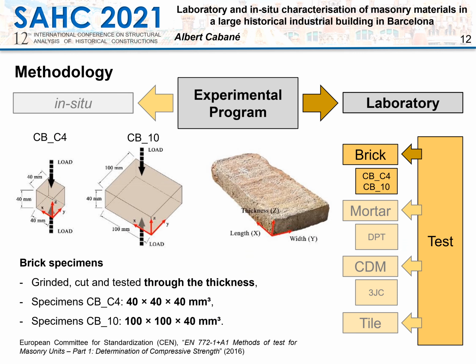The laboratory experimental characterization was carried out on the specimens produced with the extracted masonry components and core-treated masonry samples. The specimens were prepared according to the procedures specified in the European standard. Polishing the load surfaces until a constant thickness of 40 mm was obtained. At least 6 bricks were considered for every extraction zone, and 2 standard specimens for each brick were cut. Further, a second non-standard specimen was considered. The non-standard specimens were obtained from the same bricks as the standard ones. The proposed specimen was a cube with a side measuring 40 mm.